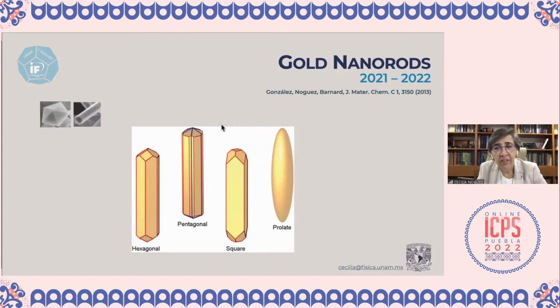Another kind of nanoparticle that we can think of, to look at these shape effects, is gold nanorods. It is very common to have decahedral nanoparticles, and then by using some chemistry, I'm not a chemist so I don't know exactly, one of these faces, let's say this one in the front, can increase in size, so people can grow nanorods in this system. The most typical shapes for the nanorods are, for example, the hexagonal, the pentagonal, the square, and the prolate.